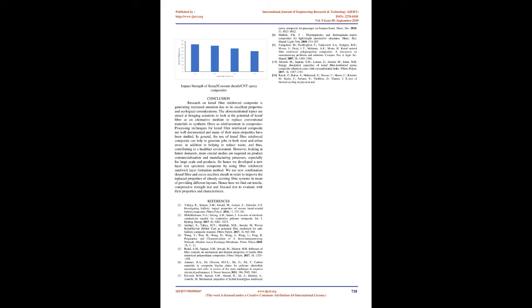This is mainly due to the dense, tight fiber architecture and higher lignin content of Cocos Nucifera Sheath compared to other natural fibers. Lignin acts as a chemical bond in the natural fibers. Higher lignin content of the Cocos Nucifera Sheath improved the bending resistance of the L2 composites. The increase in flexural properties of hybrid woven composites, L2, is also because of the combined advantage of the 2D plane architecture of Kenaf fabric and the dense architecture of Cocos Nucifera Sheath.